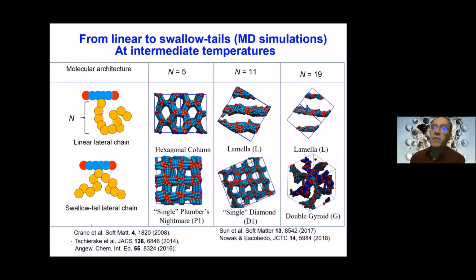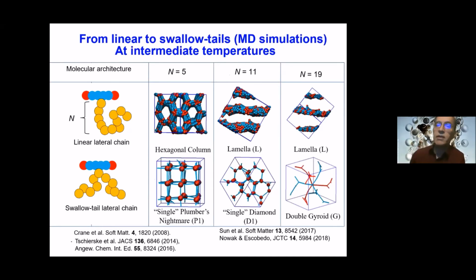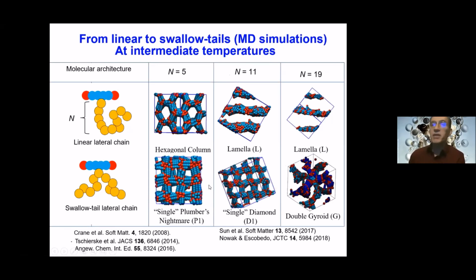So as you can see, for these examples, the phases are network phases. What you see over here is this G phase I was telling you about. But we also find, for example, this single diamond phase, which is a phase that was predicted, and it was only 2 years later that they experimentally confirmed our prediction. And you can see here, just to simplify, the skeleton, for you to see that they have these very interesting network structures.